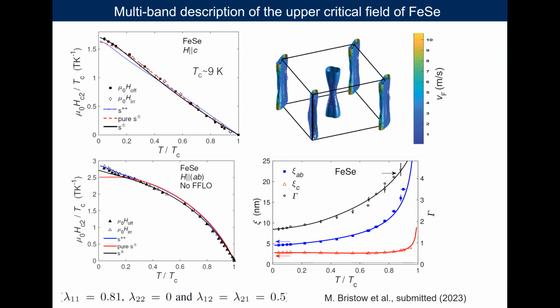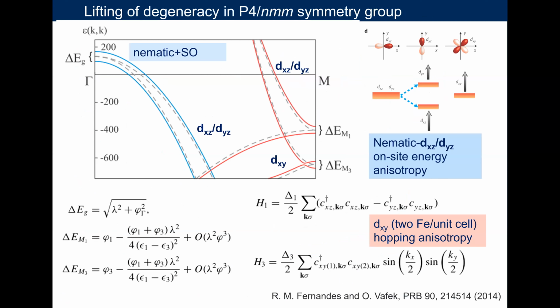So now let's look at what effects are expected when a system goes into a nematic phase. And this is a paper by Fernandes and Oskar Vafek, giving us guidance of where we should look for the nematic signature. The first one is if we look at the hole pockets at the gamma point, the splitting between the different hole bands should contain both a nematic term and also spin orbit effects. And actually, it will be given by this expression.